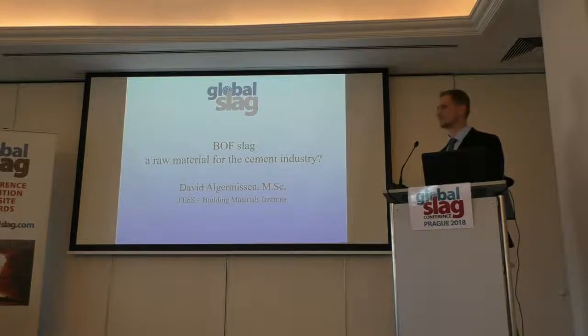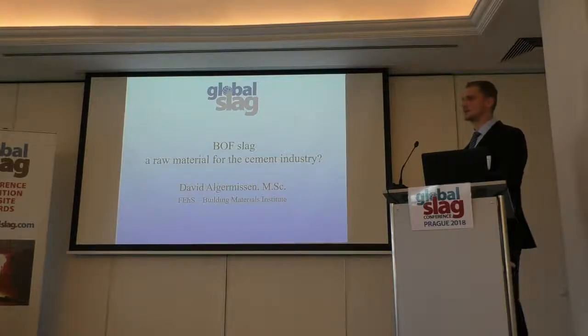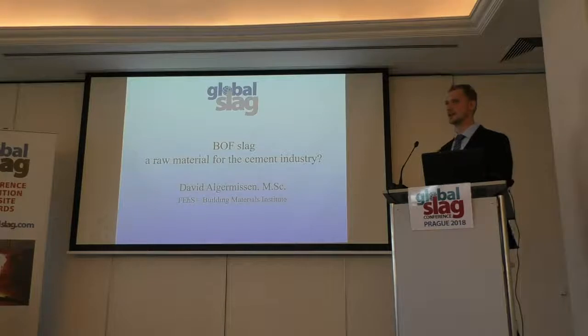Okay, we have a couple of quick questions. Are you planning any similar studies for EAF slags? We already did. Last year at Global Slag I presented our project for EAF slag, where we found out more or less the same, that we are not able to create a clinker-like material because we have to increase the lime content for the EAF slag.